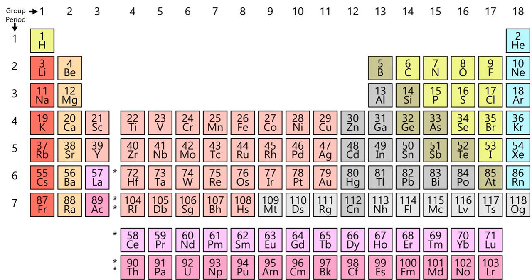Silicon is a metallic-looking, relatively unreactive solid with a density of 2.3290 g/cc and is hard and brittle. It melts at 1,414°C and boils at 3,265°C. Silicon has a diamond cubic structure and is a semiconductor with a band gap of about 1.11 eV. Silicon has a moderate ionization energy (786.5 kJ/mol), moderate electron affinity (134 kJ/mol), and moderate electronegativity. It is a poor oxidizing agent. As a metalloid, the chemistry of silicon is largely covalent in nature, noting it can form alloys with metals such as iron and copper. The common oxide of silicon is weakly acidic.